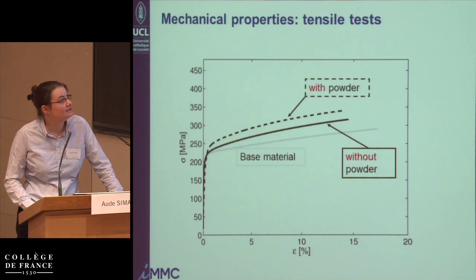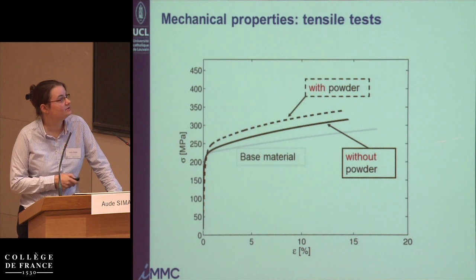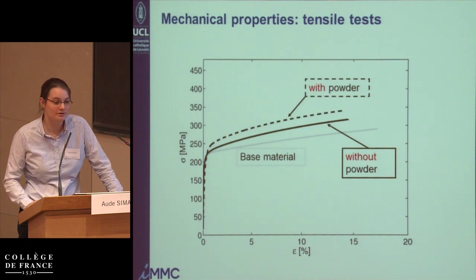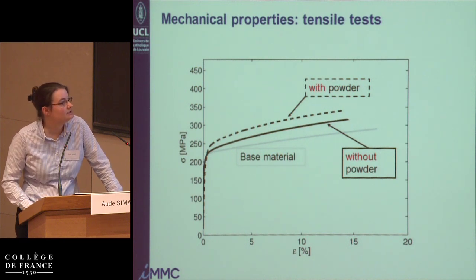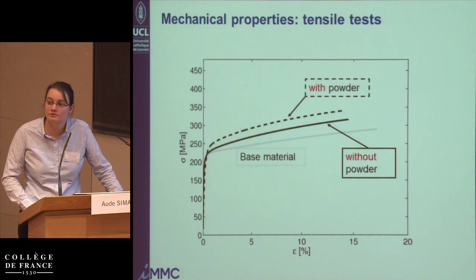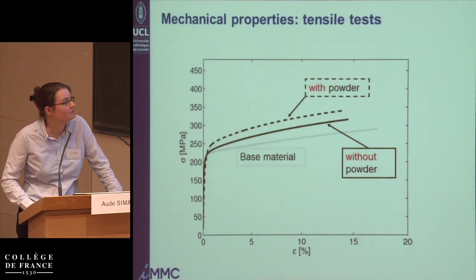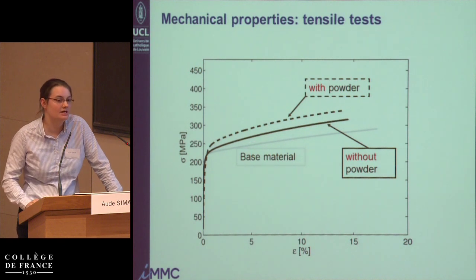So doing a tensile test on these materials, here are the results that you get. Well, this is the base material, so the copper material. And you see that with powder, you already have an improvement of the mechanical properties and more particularly of the strain hardening of the material.